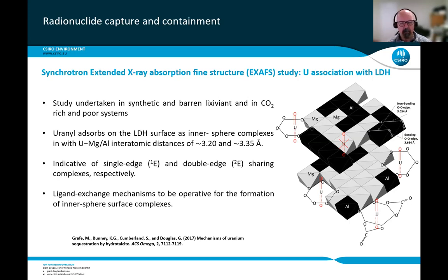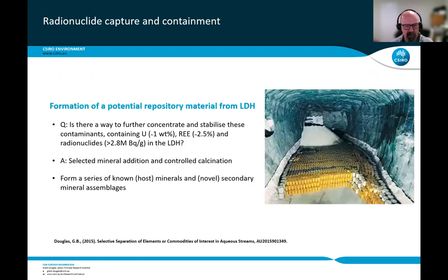Now, the really important finding out of that is that if uranium is last on when we form these in situ layered double hydroxides, it's also likely to be first off. And that's important if you're thinking about, well, can we actually recover uranium from these in situ formed layered double hydroxides? And that, in fact, is something that we're looking at the moment. So I think there's some really good prospects for actually then being able to regenerate some of the uranium from these in situ formed layered double hydroxides.